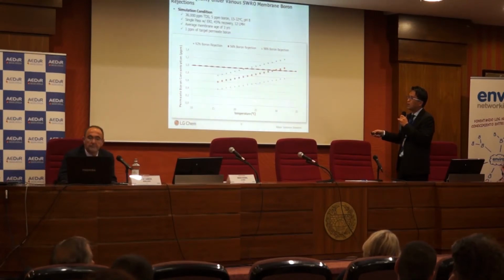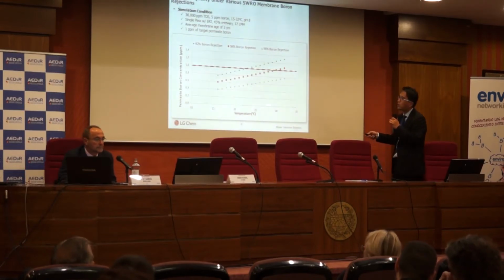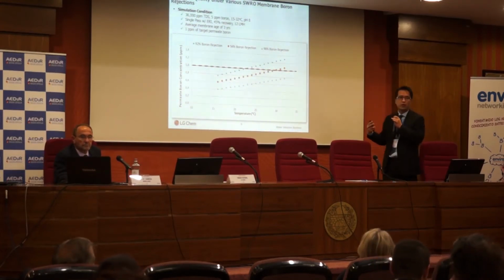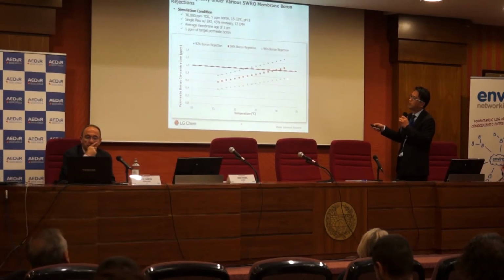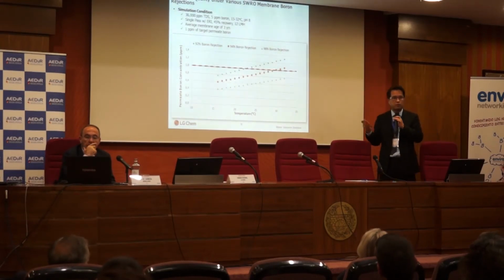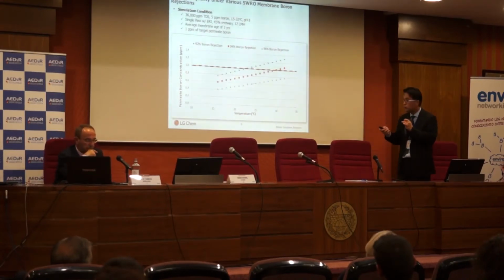rejection. So as you can see, membrane rejection is affected by several factors, but temperature is another important factor. For the 92%, the previous generation membrane, it pretty much goes above the 1 ppm limit if the temperature goes above 23 or 24 degrees Celsius. But if we have a 96% boron rejection membrane in the future, you probably don't need to worry about boron rejection even with very high temperature conditions. Our membrane, the 94% boron rejection membrane, will be fine up to 27 or 28 degrees Celsius. But if it goes above that, we probably need additional measures to deal with the boron.